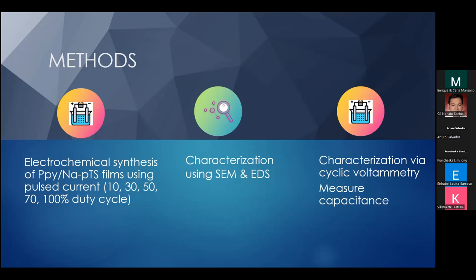And how did we characterize our film electrodes? We used scanning electron microscopy to determine surface morphology and film thickness, and energy dispersive spectroscopy to determine the elemental composition on the surface of the film. To study the capacitance properties of the films, we used cyclic voltammetry and measured the CV plots. From the CV plots, you can determine the capacitance from the area of the curve, and compute for the specific capacitance, meaning farad per gram or farad per square cm.